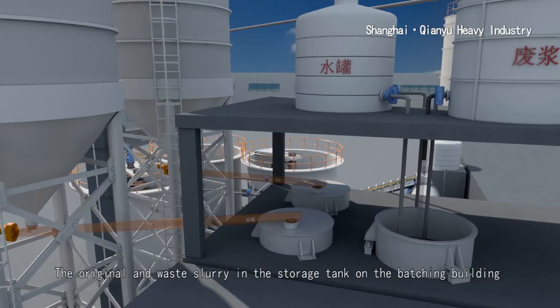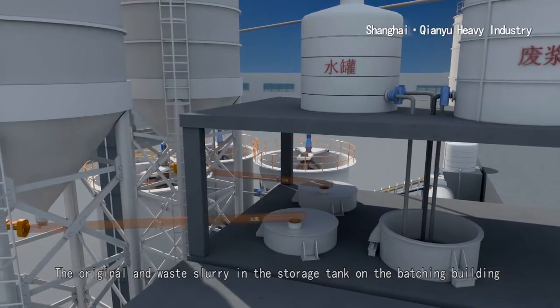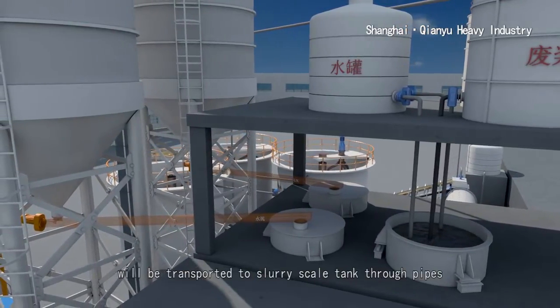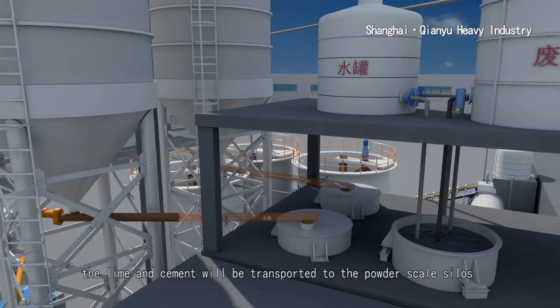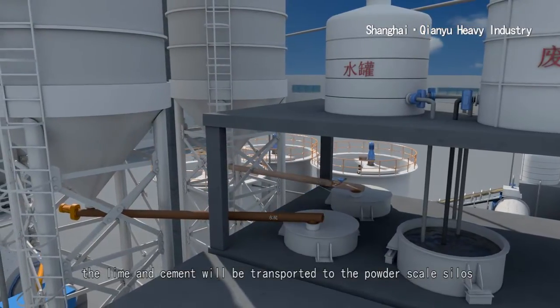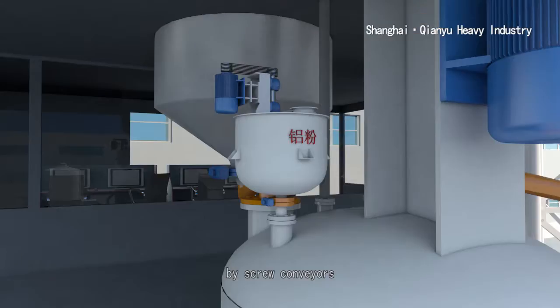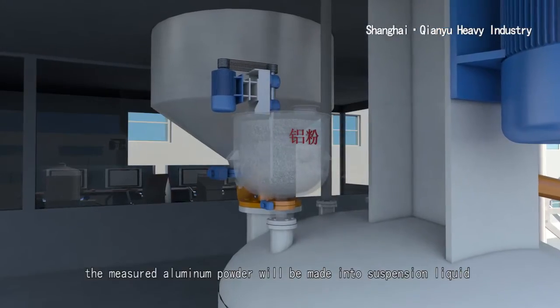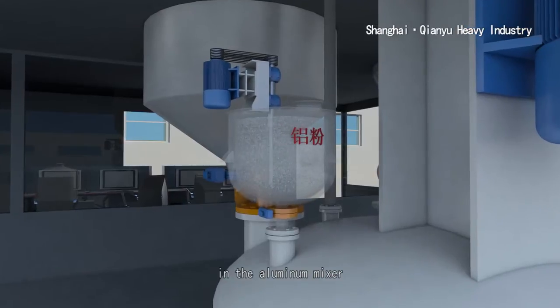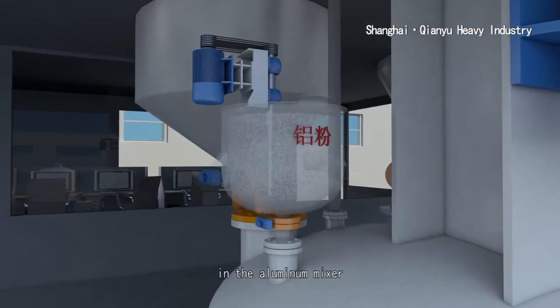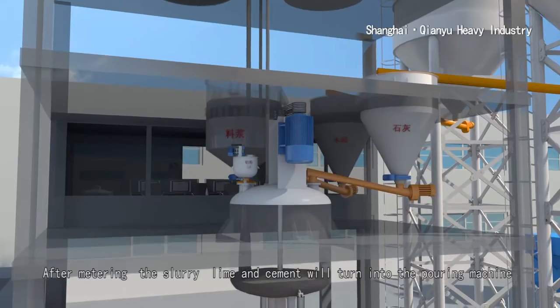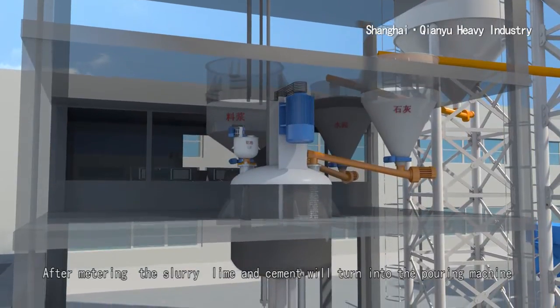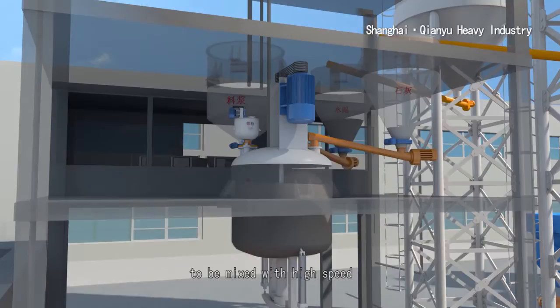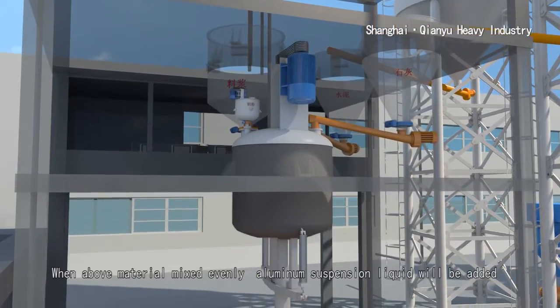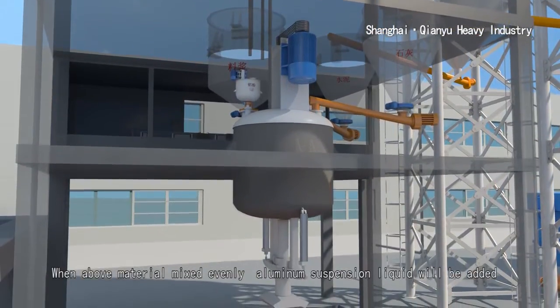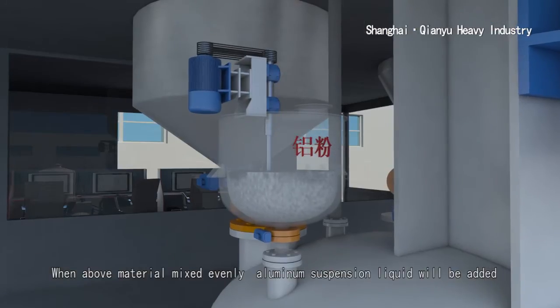The original and waste slurry in the storage tank on the batching building will be transported to slurry scale tank through pipes. The lime and cement will be transported to the powder scale silos by screw conveyors. The measured aluminum powder will be made into suspension liquid in the aluminum mixer. After metering, the slurry, lime, and cement will turn into the pouring machine to be mixed with high speed. When above material mixed evenly, aluminum suspension liquid will be added.